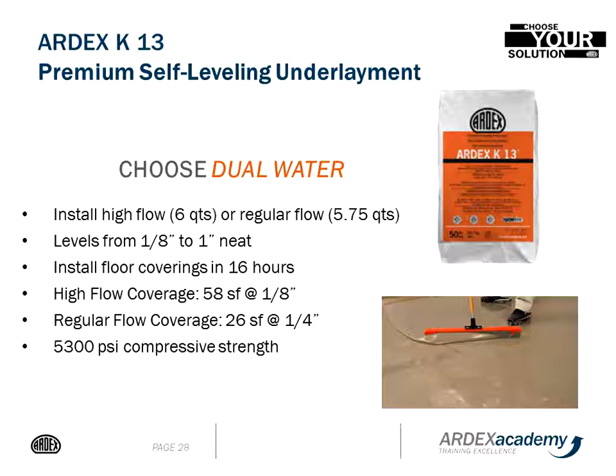Even at the high flow ratio, very high compressive strength, a lot of horsepower behind this product, 5,300 PSI compressive strength. Really strong material, really versatile. Variety of different substrates from concrete to ceramic, quarry, porcelain, adhesive residues, standard substrates that you see on commercial installation.